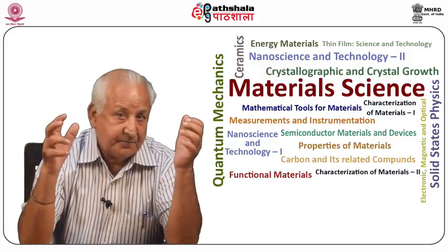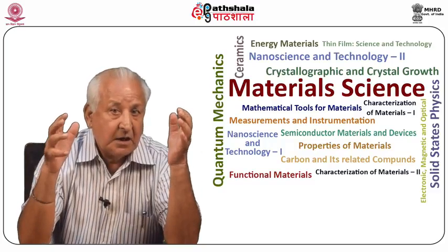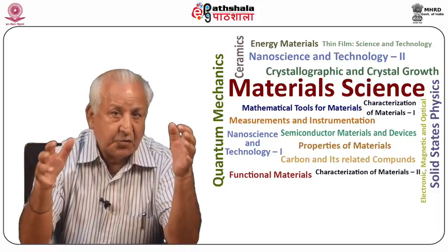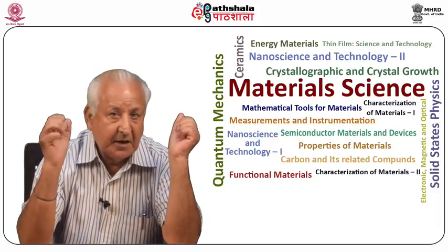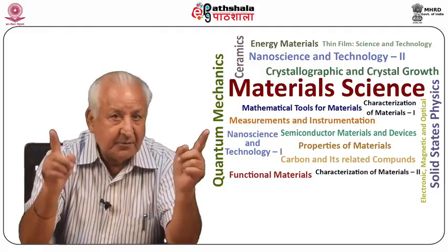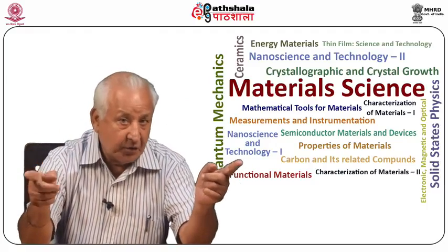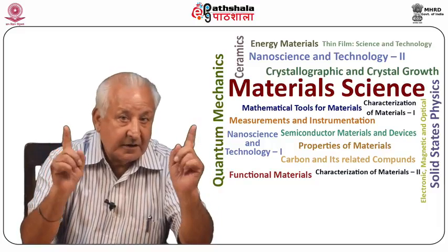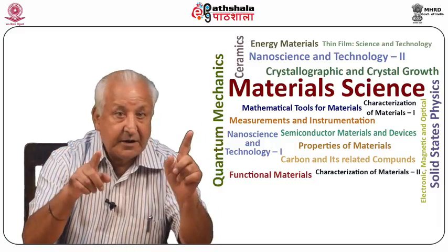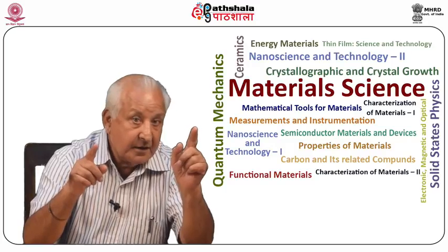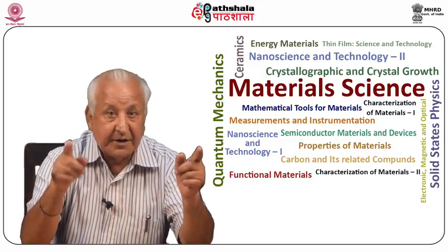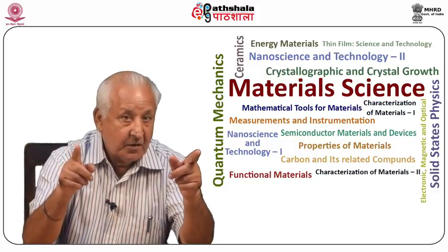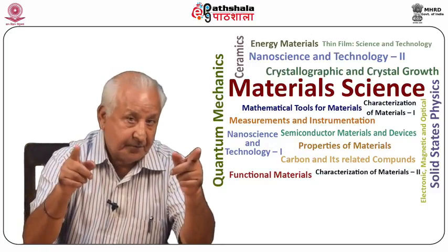If the sphere, known as Ewald's sphere, does not pass through any points, it will suggest that the particular wavelength in question will not get diffracted by the crystal in that orientation, and readjustment of orientation will have to be carried out for diffraction to occur.